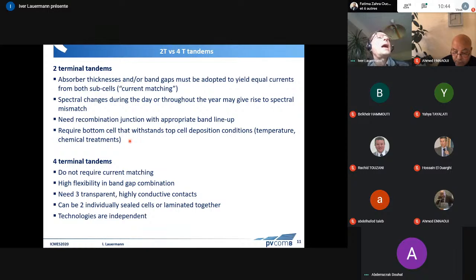And what is important, when we deposit the top cell onto the bottom cell, we cannot use high temperatures because otherwise we'll destroy the bottom cell. And that's why these perovskites are so advantageous. In a 4-terminal tandem, we do not require this current matching because we have 2 independent devices. And so we can combine many different band gaps, thicknesses, and so on. But we need 3 transparent, highly conductive contacts because we need those terminals.